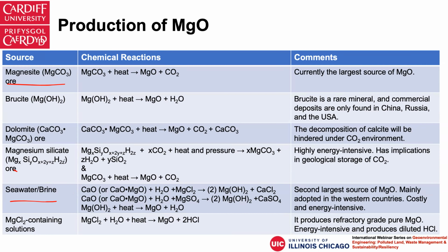And then the middle one, the magnesium silicate ores, is the one I think is very promising, because chemically it is carbon neutral. In the first place it absorbs carbon dioxide to produce magnesite, and then releases carbon dioxide out. So chemically it is a carbon neutral process. But the problem at the moment is that the whole process of getting the magnesium silicate to carbonate is highly energy intensive. The reaction only happens at very high heat and pressure in order to increase the reaction rate to have the magnesite in the end.